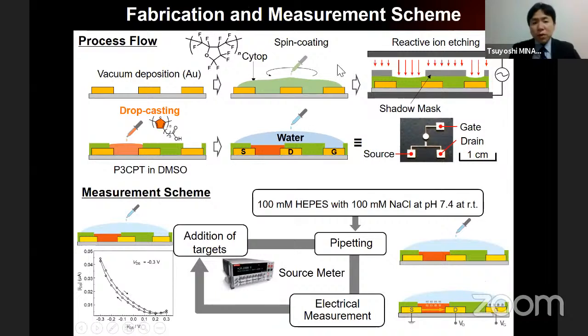So here is the fabrication process. We employed a side gate structure. That is a very simple way; even a part-time job person can fabricate the device. We just drop the water and then measure the target, measuring the electrical properties. So here is a scheme: the addition of target and pipetting water, and electrical measurement. And we repeat this cycle.